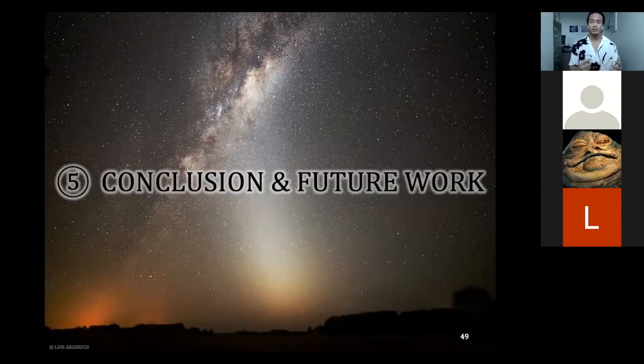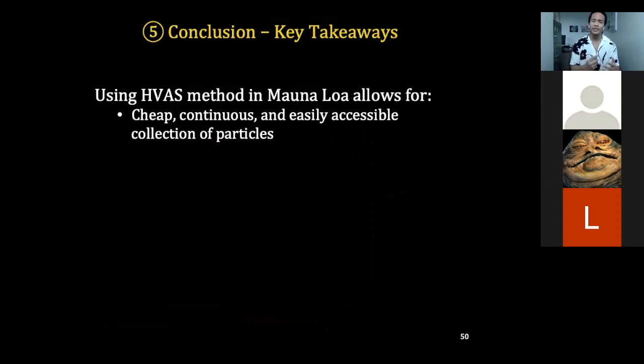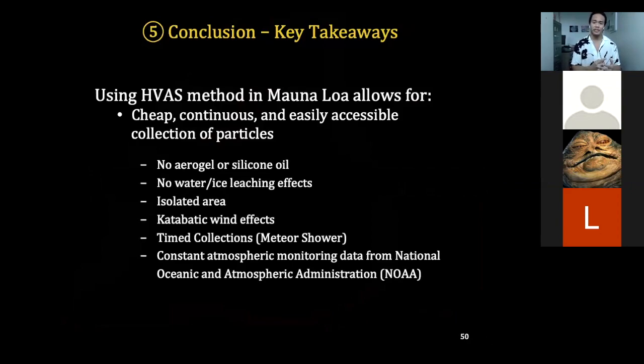Now moving on to the conclusion and future work of my project, starting with some key takeaways. Using the high volume air sampling method in Mauna Loa allows for cheap, continuous, and easily accessible collection of particles without the use of contaminants such as aerogel or silicone oil, without the leaching effects caused by prolonged exposure to water, ice, or snow. And it's done in an isolated area that experiences katabatic winds. On top of that, we can do timed collections when our collaborators let us know that there are meteor showers, and we get constant atmospheric monitoring data from our collaborators at NOAA.